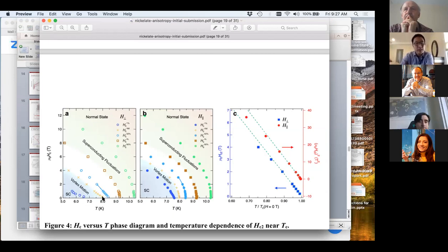our analysis is qualitatively robust, meaning some of the numbers change a little bit, but what we see is the same. But outside of these thresholds, so above 80, 85% or so, or below 20, 25%, we feel that we're clearly going into a different regime. And one of the ways you can see this is in the perpendicular direction, where we have what we're interpreting as orbital depairing. As we go to higher and higher threshold criterion, we're changing even the functional form. Right? So that's what we know at present to address your comment.